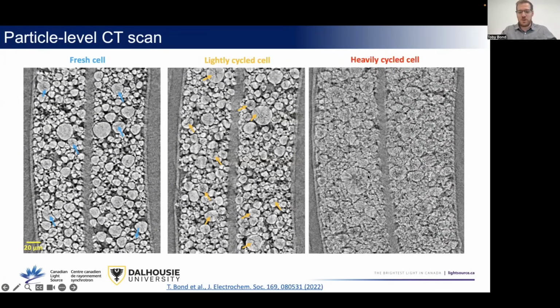The material is almost completely disintegrated, and there are so many cracks. You can tell that there's probably electrolyte filling all of these cracks and infiltrating the snowballs, the secondary particles I was talking about before. And when it's so extensively cracked like this, the layer swells up. So this layer is a lot thicker than these other layers, because there's a lot of extra empty space in here. And so there's much more exposed surface area.